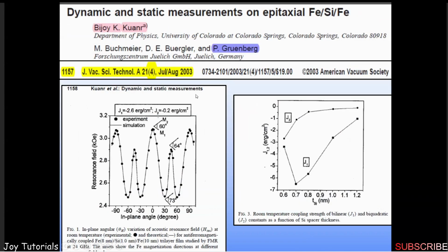In this work, we tried to explain, again from dynamic and static measurements, the iron silicon iron layer. The fitting of this gives rise to the exchange coupling. This indirectly gives the GMR, the giant magnetoresistance. What you can see here, the interesting part, is how the magnetizations are aligned to each other in the tri-layer structure. That is, M1 is the magnetization of the bottom iron layer, M2 is the magnetization of the top layer, how they are aligned at different angle rotations, and the exchange coupling through the silicon spacer.